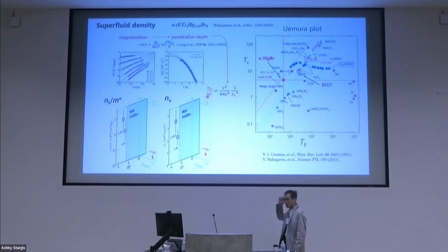We searched for the Fermi surface, but under pressure, cracking occurs. So maybe from 0.3 gigapascal to 1 gigapascal. But at 1 gigapascal, the ratio exceeds 100. So we observe.